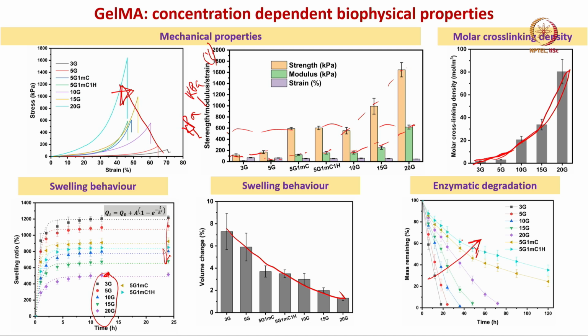Now, mass change, mass remaining like in the enzymatic degradation case, these also shifted in this way with larger concentration of GELMA. So, what you see here is that after 5 days, if you formulate a new hydrogel composition like 5% GELMA with hydroxyapatite and modified carboxymethyl cellulose, you can have almost 30% of the scaffold still remaining after 5 days of enzymatic degradation, whereas with 3% or 5% GELMA everything gets degraded even within 1 day of the enzymatic degradation studies, where they use this collagenase solution.